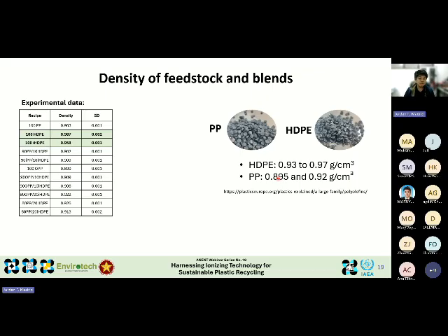Earlier, we mentioned that electron beam irradiation at low doses did not lead to cross-linking in high-density polyethylene, but it could have resulted in some degree of chain branching. In the next few slides, I'll show a simple measurement of density that can actually provide evidence to support this claim.